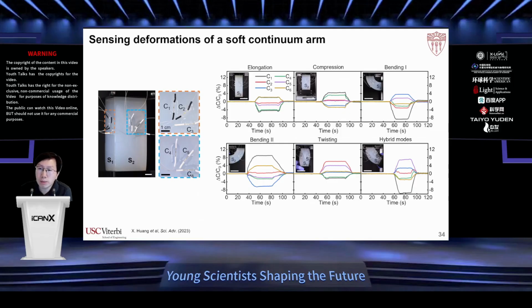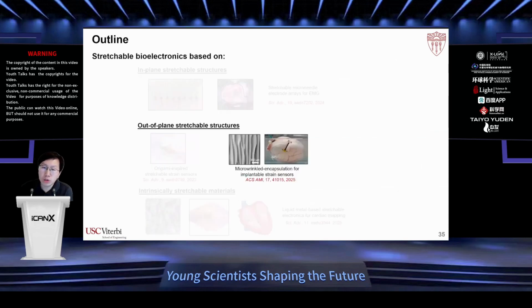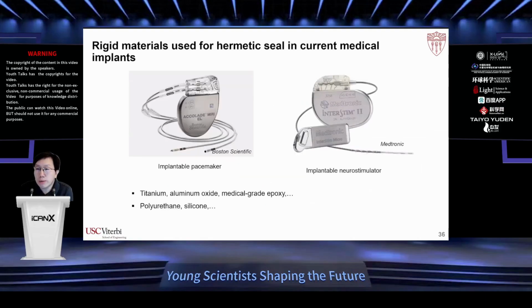So here we haven't really demonstrated the biomedical applications, but in a highly related project, we show that, in order to develop strain sensors that are implantable, we also need to solve another challenge, which is encapsulation. So we know commercial implantable devices typically use rigid materials such as metals and metal oxides to achieve hermetic seal, which means that we want the device to prevent penetration of biofluids so that they can operate for a long time, months or even years, decades.